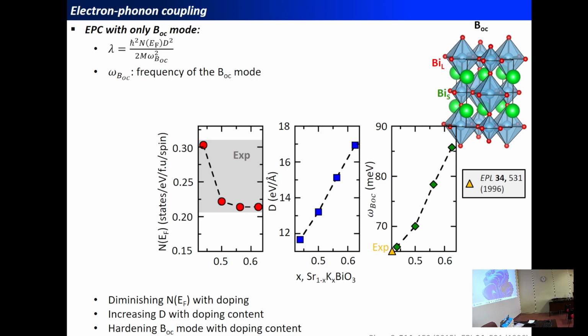And we end up with a mode that is hardening upon putting more and more holes in the system. And at the lowest doping content we can model in our system, the frequency of the mode we extract is reminiscent of what is observed experimentally, which is around 64 meV for this frequency. So further showing the quality of the SCAN functional to model the properties of these bismutates.